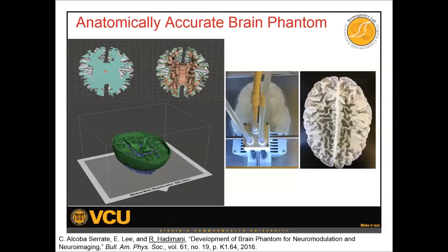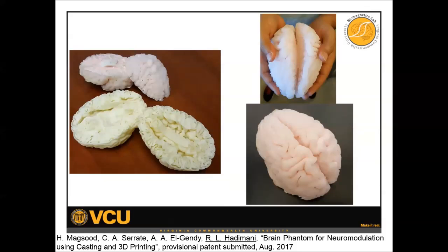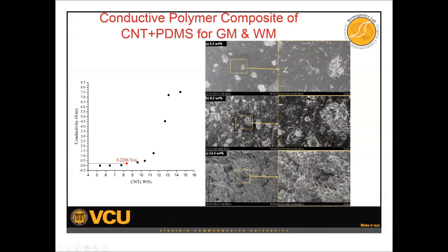So in this view graph, on the left-hand side at the bottom are the shelled gray matter areas. And on the right, here is a full gray matter, white matter combined brain with a polymer. So basically, we create different shells of gray and white matter, and then pour this polymer into these plastic shells. And then we dissolve these plastic shells, which doesn't affect the polymer. But these polymers are non-conductive. So we had to make our own conductive polymer.